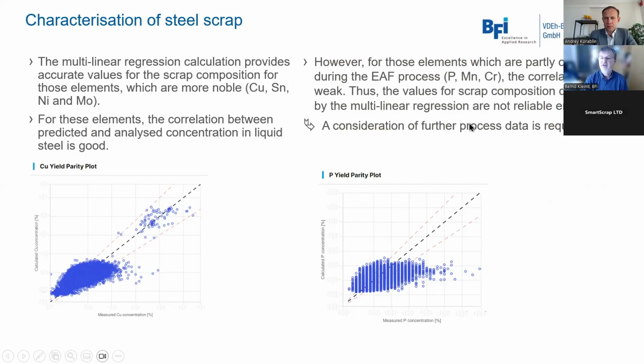So that means that the values for the scrap composition, which are determined by the multilinear regression, are not really reliable. And this means that a consideration of further process data is required. You can see here that you have not a very good correlation between calculated and measured phosphorus concentration when using the multilinear regression calculation, which makes it difficult to achieve the limit values for phosphorus in the liquid steel.